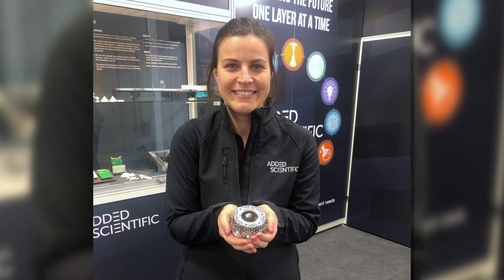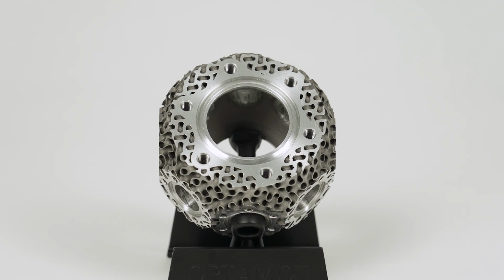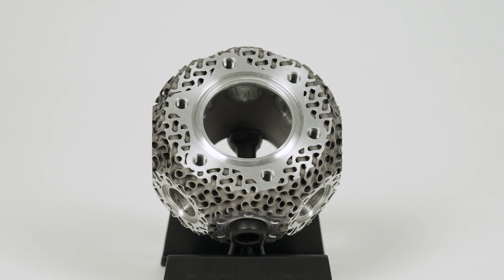Okay, so that gyroid, that's an example of a surface shape complexity you could only get through additive manufacturing. So let's talk about that. What is the additive process that produced this? So this was built on a Renishaw AM250 laser-based powder bed fusion. We've talked about that before. The engineer who built it, her name is Sarah Everton. And this part was printed initially, and then it had to go through a couple of post-processing steps, so a few rounds of heat treatment, and then finish machining for these shiny faces that you see. Okay, so that's how it was made.